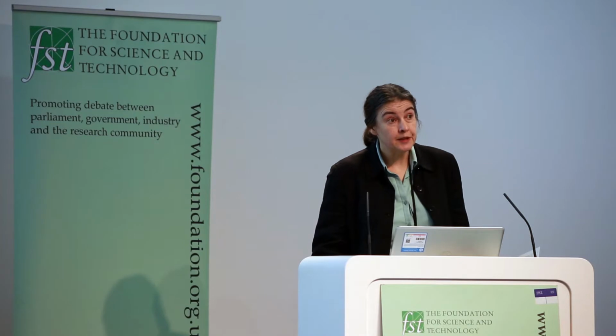So to put this in context, you also have to remember that since the lithium-ion battery was invented more than 25 years ago, its energy density has gone up, and it's gone up from new materials, better engineering, putting more stuff into the same volume, and its price has gone down by more than a factor of 10, but we are reaching close to the theoretical limits. New approaches are needed. So we can't just go on projecting increased energy densities of batteries without coming up with new chemistries. And we can't think about putting the same amount of material into the same volume without safety issues.